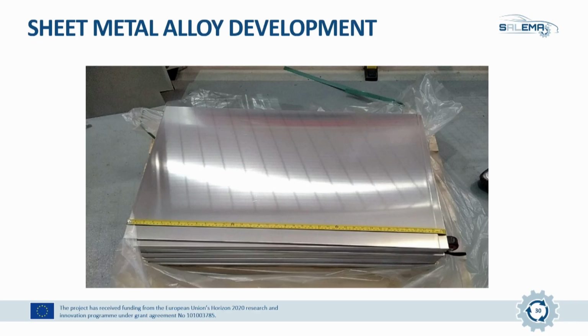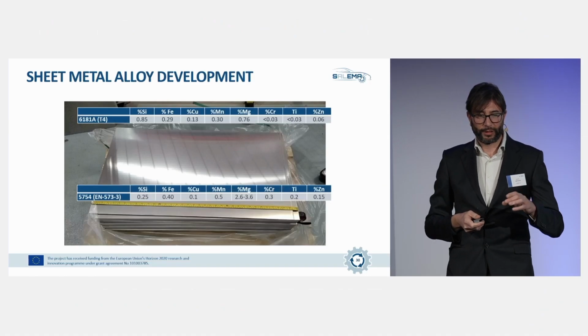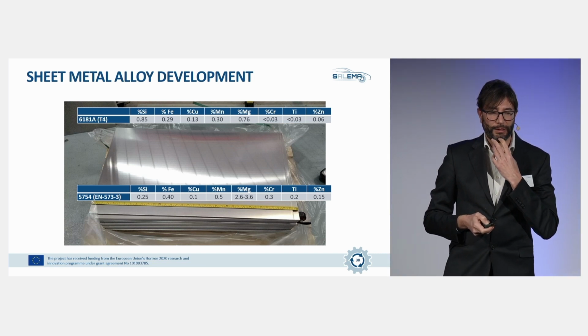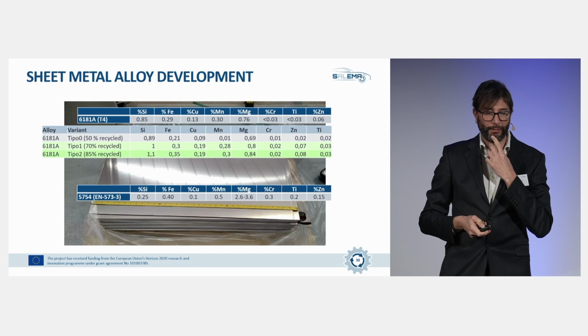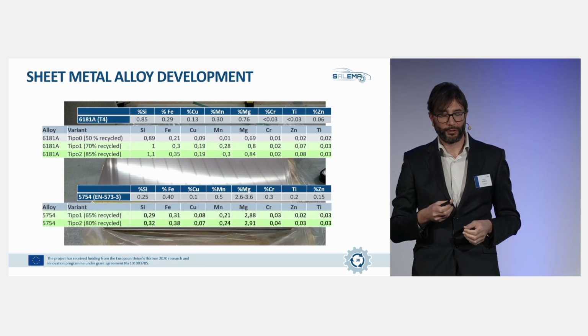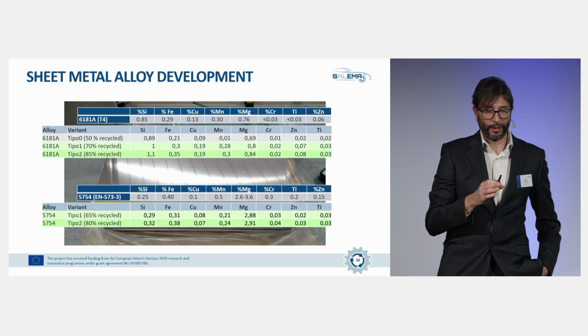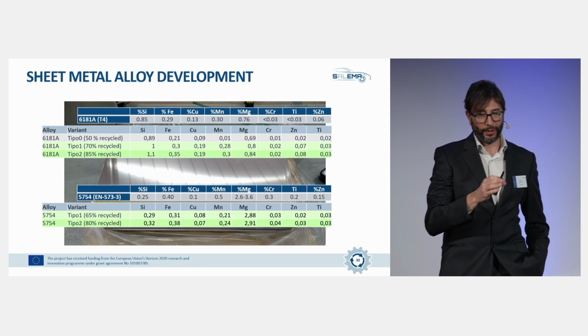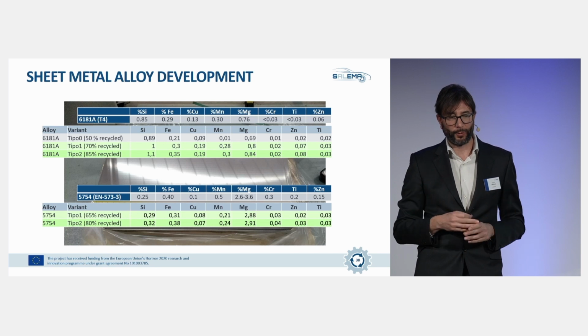That regarding high pressure die casting. Then I will shortly present also the alloy development process followed for stamping. On stamping, we select 2 alloys for the partially recycled development. One, the 6181A, a 6000 series alloy, and 5754, a 5000 series alloy. And we did it with 3 different recycled contents for the 6181 and 2 different recycled contents for the 5754.